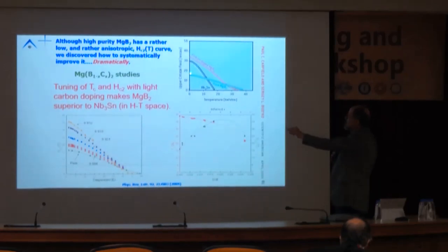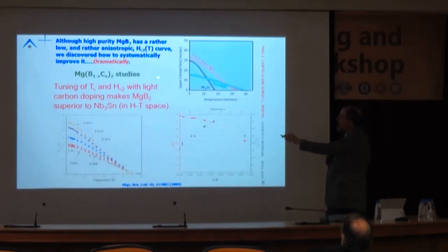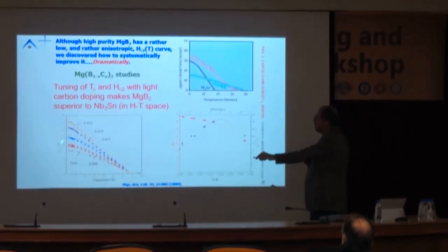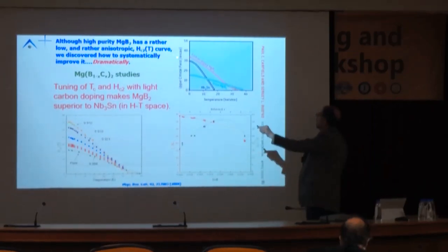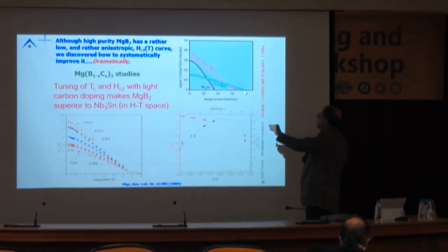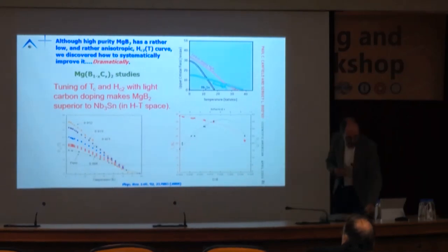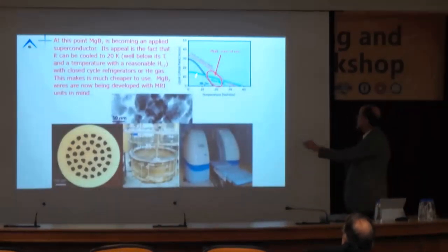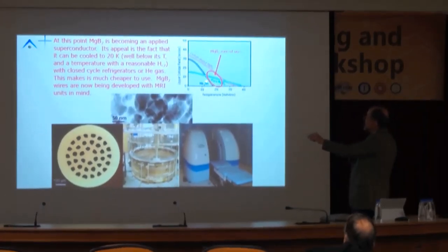On the other hand, if we can shorten the electron mean free path, for example, by doping in carbon, we can add 1, 2, 3, 4, 5% carbon, and we can go from 15 to 20 to 25 to 30 to 35 Tesla. Bulk carbon-doped MgB2 supersedes the Hc2 phase diagram for niobium-tin over the whole temperature range, and perhaps more importantly, we have what's now, 15 years later, called the MgB2 zone of use, 20 Kelvin.